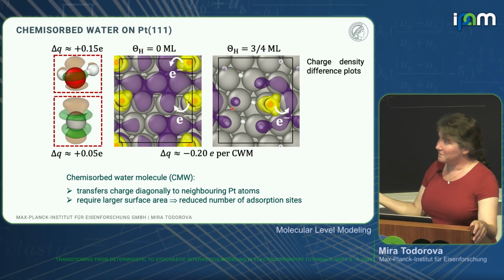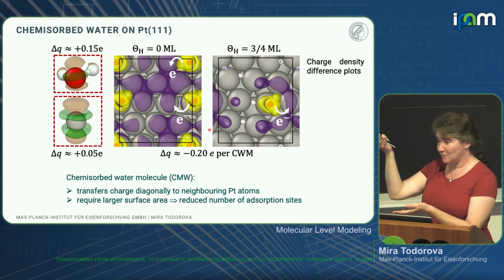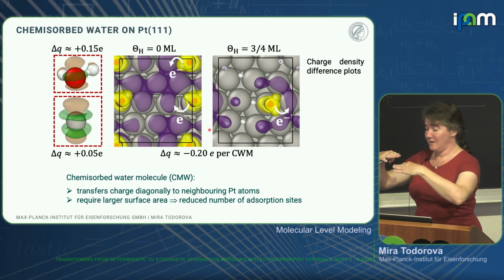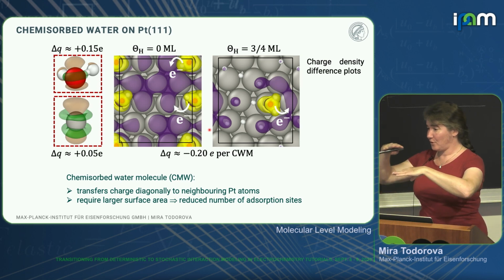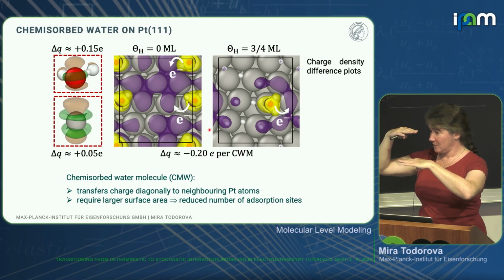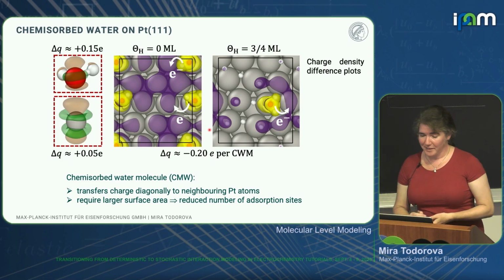And obviously, at some point, the hydrogen wins this competition so that the water desorbs. When you have a completely hydrogen-covered surface, then the surface is hydrophobic and the water is moving up. So we do see that there is a difference, and you create a hydrophobic gap.